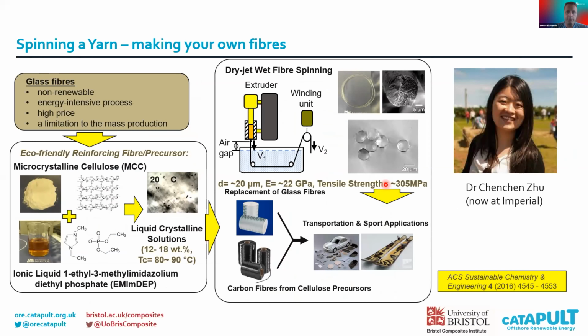We've been spinning our own fibres as well. Sometimes you need a long fibre, but that's not always possible with natural fibres. They have very limited lengths. So we've been making fibres, spinning them in a novel ionic liquid solution. Ionic liquids are interesting because they're a so-called green solvent. They're much better for the environment than things like viscose. And so we've been making fibres using the ionic liquid 1-ethyl-3-methylimidazolium diethyl phosphate. We've also been combining some of the solvents with other solvents to get mixed solvent systems. And we've been able to make some pretty reasonable fibres with decent enough properties.